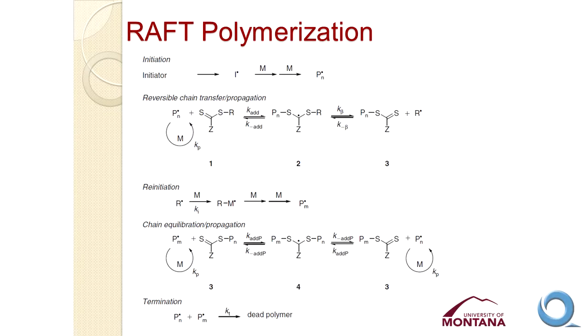So in conventional free radical polymerization, we have monomers, and we add an initiator, we initiate the reaction, and it runs pretty much at random and very rapidly. We generate polymers, adding another monomer in a rapid free radical reaction, and that reaction is terminated when two of those growing polymer chains find each other and terminate the reaction to form a dead polymer. There's nothing wrong with that technique, of course, except that we typically will generate very polydisperse polymers because the rate of propagation, because of the different times of initiation, and because it's a random process when these polymers find each other to terminate, we get very broad distributions in molecular weight.